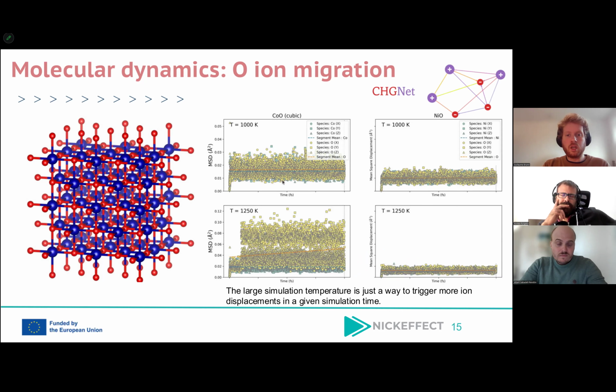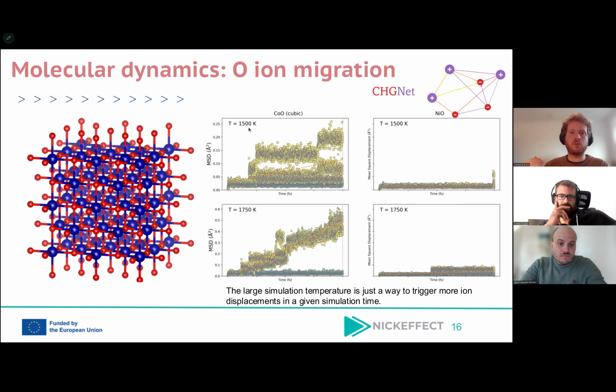We have to look at the yellow dots here for oxygen, and this shows the mean square displacement. And how to interpret this is basically if this stays around zero, then the oxygen atoms are not moving, basically. And the higher it goes, the more the oxygen atoms move in the crystal. So you see that on the left, there's a bit of movement, but not that much. On the right, there's nothing at all. And then if we crank up the simulation temperature, so the simulation temperature is high, but it's just to trigger more events. It's to see more of what's happening in a shorter simulation time. It's not the actual temperature of the system that they're doing in the lab. It's just for the simulation.